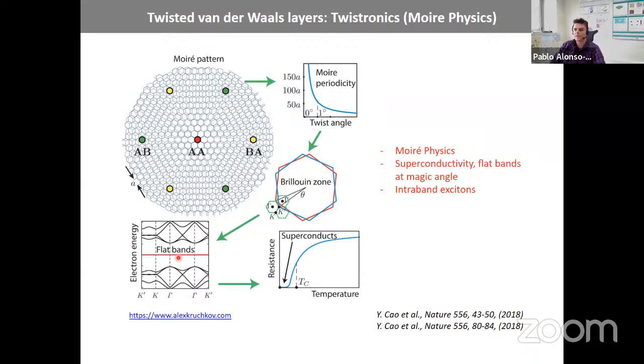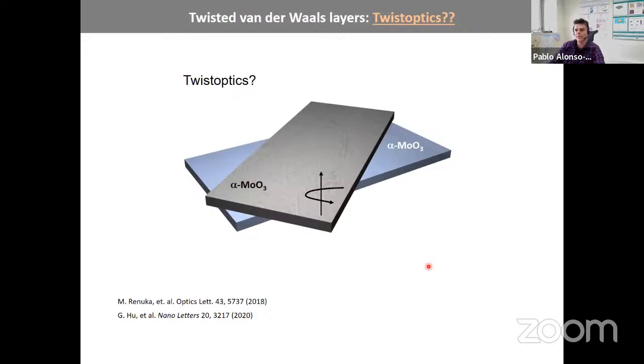Of course, the physics here is completely different. When you have graphene and then you rotate the graphene, you know that there are these super nice experiments where they can see superconductivity, flat bands at the magic angle, and so on, between the two graphene layers. But that is more electronic physics, electronic bands, and so on. But what will happen if we now take two slabs of this material, MoO3, and rotate one relative to the other? Now, we can think of polaritons, surface electromagnetic waves, classical electromagnetic waves that can hybridize with other surface waves in the material below, and by this hybridization, maybe new kinds of propagation could be observed. This was the initial hypothesis for this kind of twist optics.